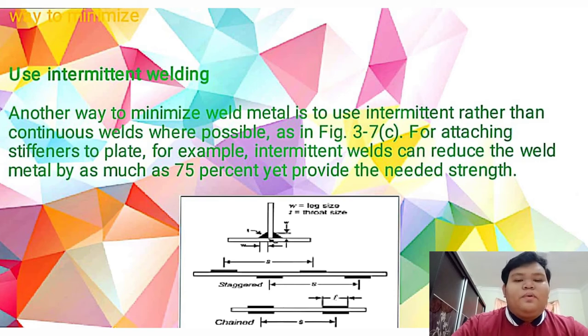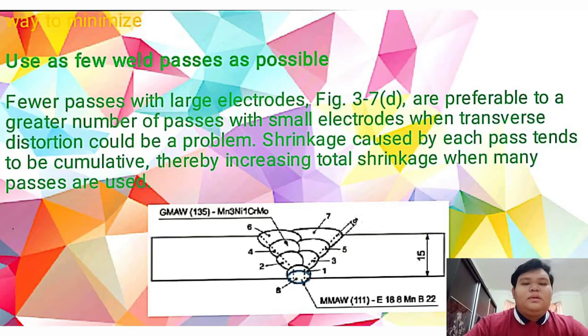For attaching stiffener to plate, for example, intermittent weld can reduce the weld metal by as much as 75% yet provide the needed strength. The next one is use as few weld passes as possible. Fewer passes with a large electrode, figure 3.7d, are preferable to a greater number of passes with small electrode when transverse distortion could be a problem. Shrinkage caused by each pass tends to be cumulative, thereby increasing total shrinkage when many passes are used.